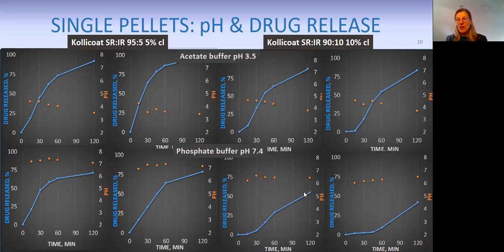Even more pronounced when you expose the same batch of pellets to phosphate buffer 7.4. Drug release is not complete at all. We only reach like half of the drug of the core. The pH is not going towards 7, rather around 6. And the second pellet from this very same batch is only releasing after 45 minutes. So here we've got a very long lag time before drug release onsets. And you can see the pH in the pellet is also not going towards 7.4.